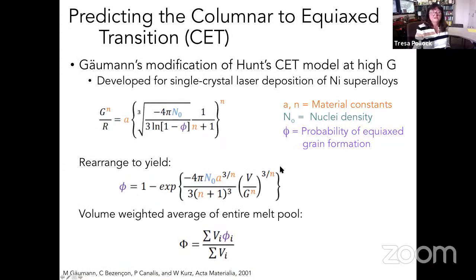Now, why might we want that information? Well, because we want to be able to connect the processing parameters to the structure that develops. And so if you study solidification, you know that the main parameters are the thermal gradients at the interface and the interface velocity. And there are models for how one transitions from that columnar to equiaxed structure. And all of these models require information about the density of nucleated grains and information on the material itself. But the missing information in many of the models that have been applied to additive manufacturing is this nucleation density.